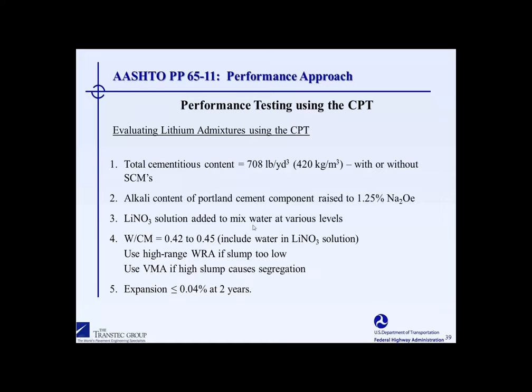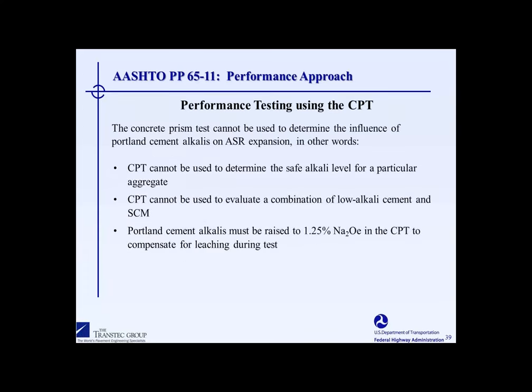So this is just showing some of the details here, but this is essentially identical to ASTM C1293. And we also allow for the use of testing lithium admixtures in this procedure. So lithium-based admixtures can be used directly in the concrete prism test. You do have to wait 2 years for those results, like you would with testing SCMs. So I did want to at least make the point that the concrete prism test is suitable for evaluating lithium admixtures.